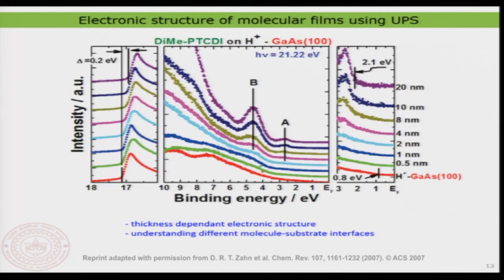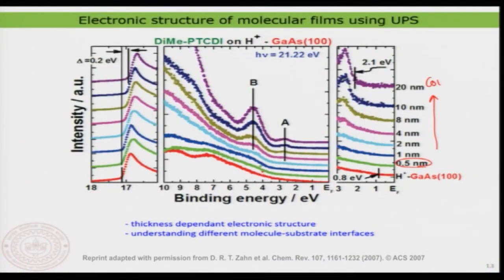Now, I want to show you a few more examples. I can now study the electronic structure evolution as a function of thickness. It is again a similar molecule to what we have seen in the previous case, the same molecule, but now I am depositing and increasing the thickness of the layer. You can see here it is 0.5 nanometer, showing a sub monolayer coverage. And here the coverage is increasing, and as the coverage increases, you can see the electronic structure is also slightly modifying.